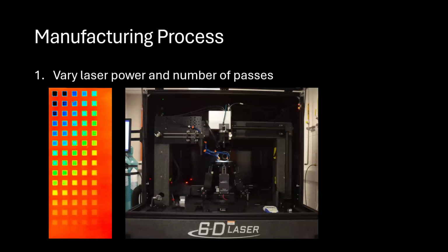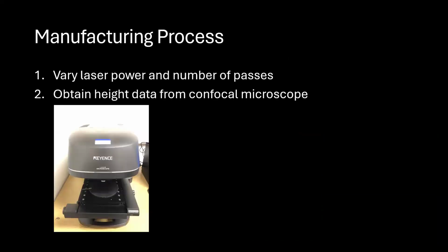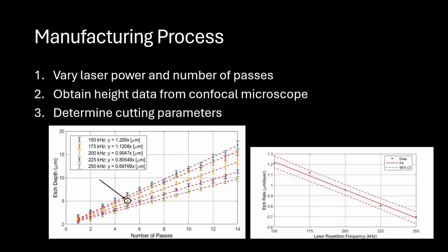Our multi-step manufacturing process begins with a grid of rastered cuts on our custom femtosecond laser micromachine, in which we vary laser power and the number of passes. Next, we obtain the height data from a confocal microscope. Finally, we used a MATLAB script to create graphs comparing etch depth as a function of number of passes and laser power. We selected 200 kilohertz repetition frequency and 5 passes for our parameters as a trade-off between material quality and manufacturing time.